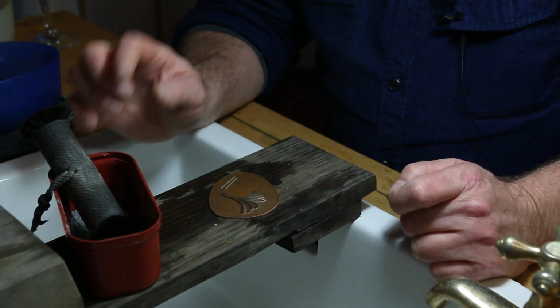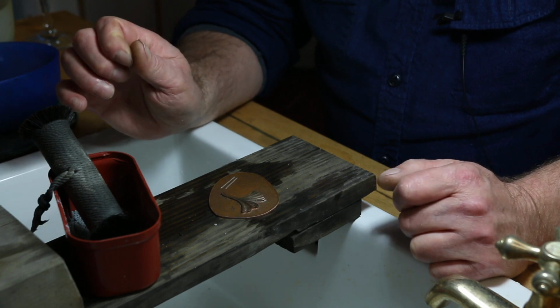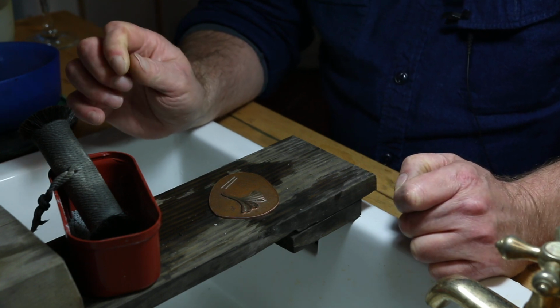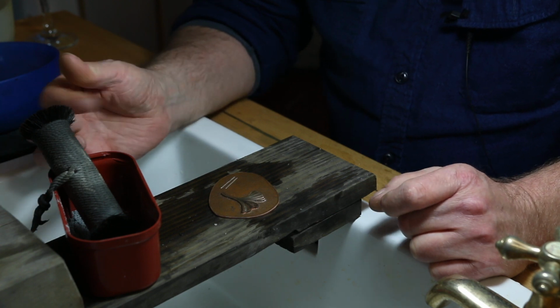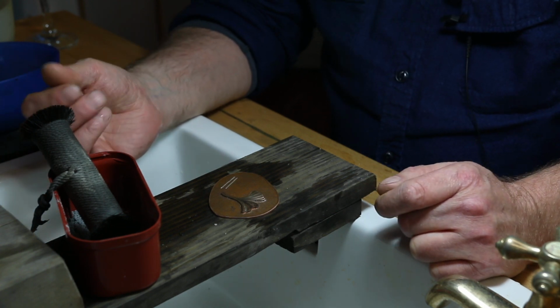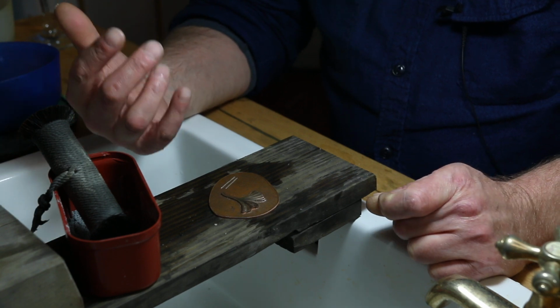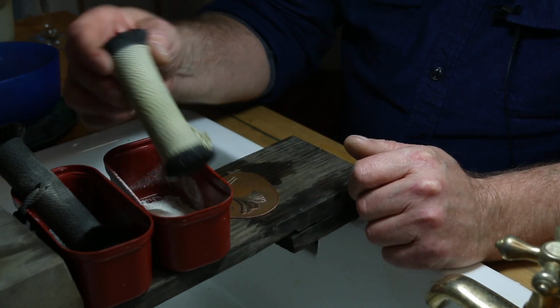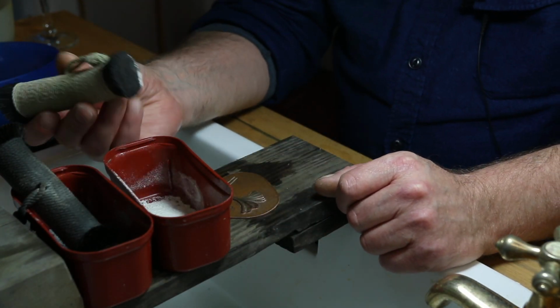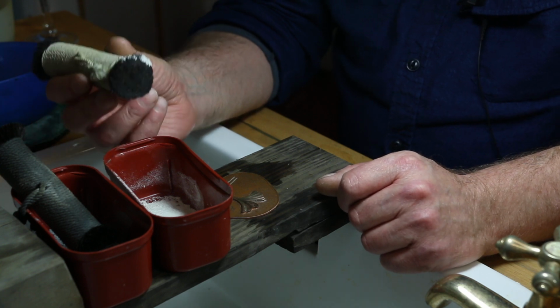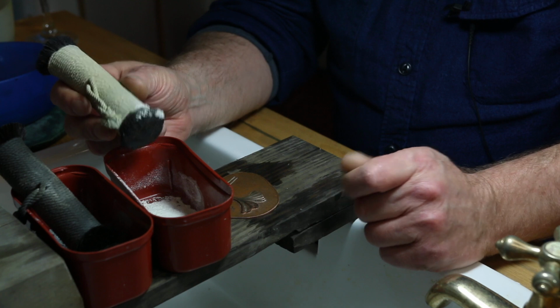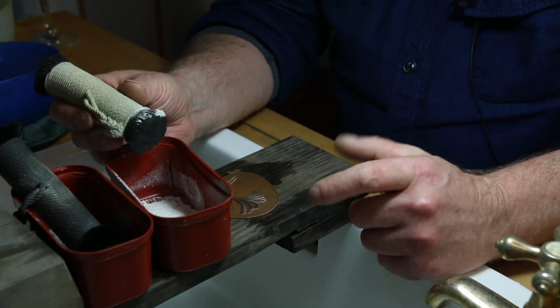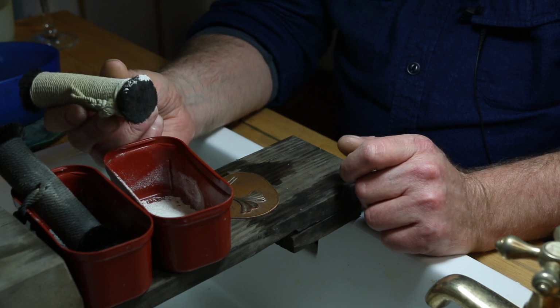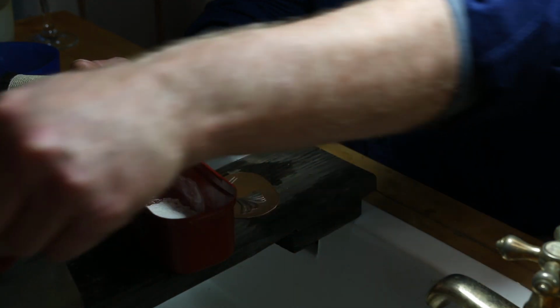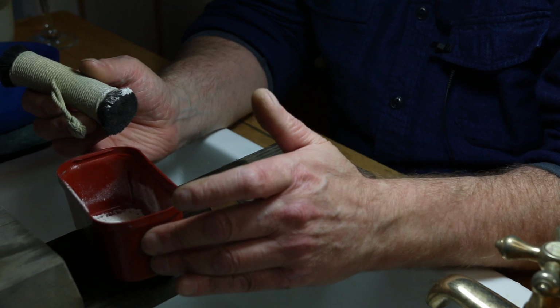Right, the polishing compound I use, traditionally it would have been tonoko, which is a very finely ground fire clay. It has a very similar consistency, texture and grit to pumice. I use pumice now quite a lot. I like pumice. This is 120 grit pumice, and I'm using a traditional Japanese horsehair brush. You can use a toothbrush or any other similar short, stiff bristled brush, with water as a slurry. Pumice will give you a matte finish.